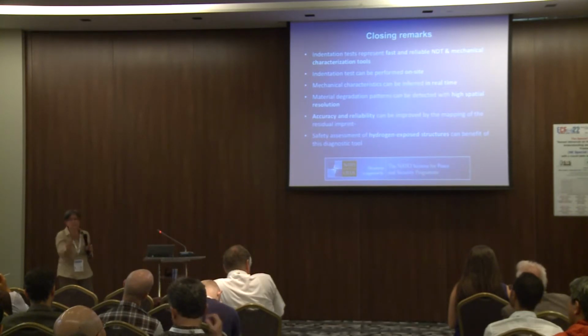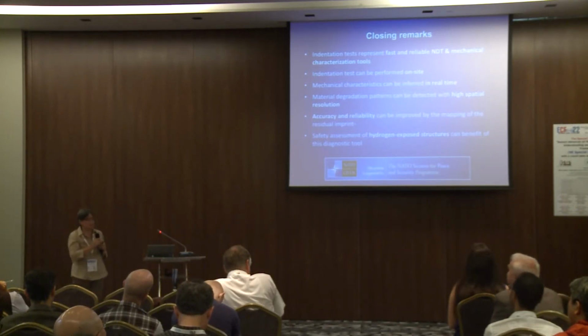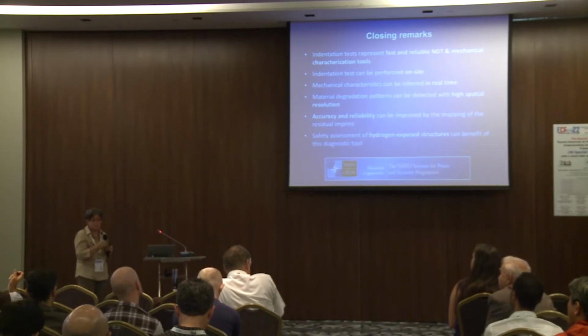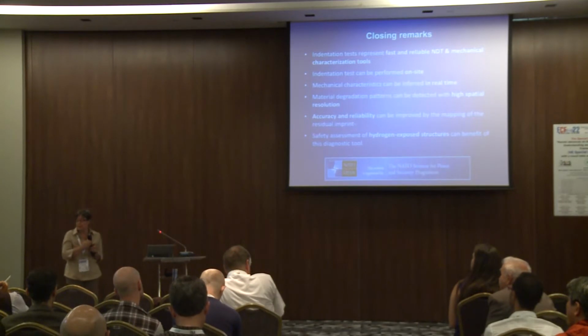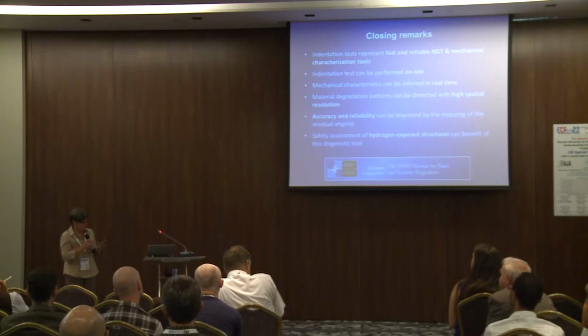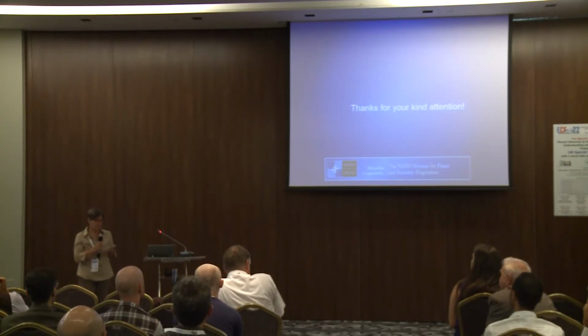And at the end, we believe that also hydrogen-exposed structures can benefit from this kind of diagnostic tool, especially in those cases which we heard about this morning, where the change in the bulk material properties can lead to failure much before any crack appears on the component. And with this, I thank you very much for your attention.